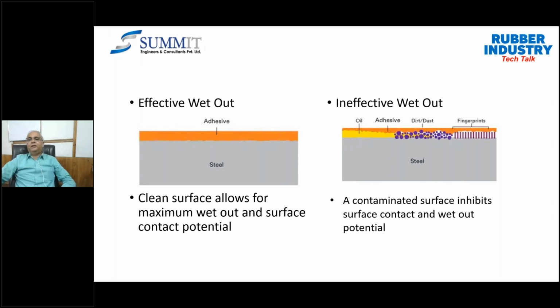This bond failure could happen quickly, immediately, or over a period of time. This cannot be predicted, because that will depend upon the behavioral pattern of this dust which is sandwiched in between the adhesive and the substrate. If it gets switched off over a period of time, that again changes the behavioral pattern, and then it can create a problem for you, right? So we should keep in mind that we must ensure effective wet-outs for any type of coating application.